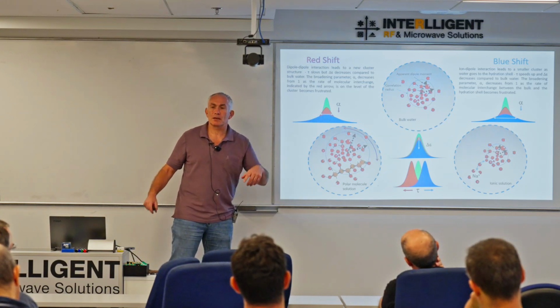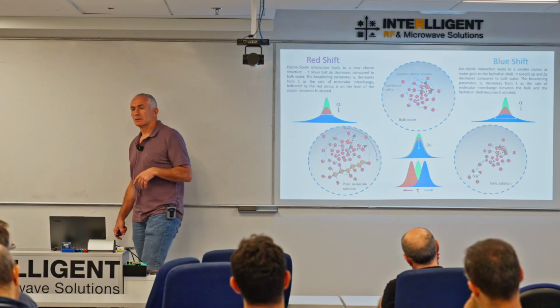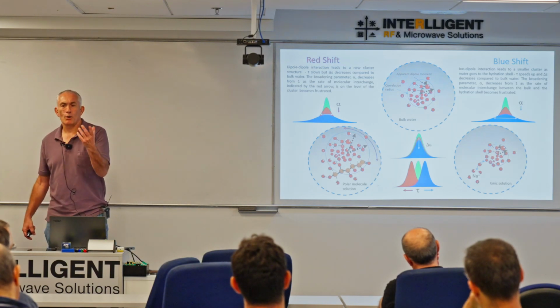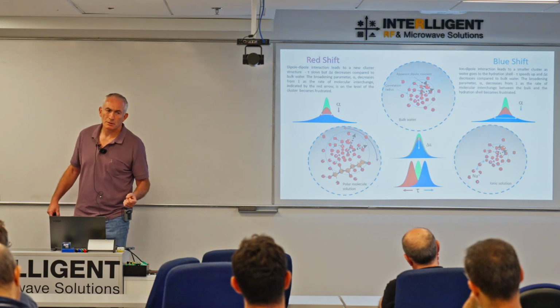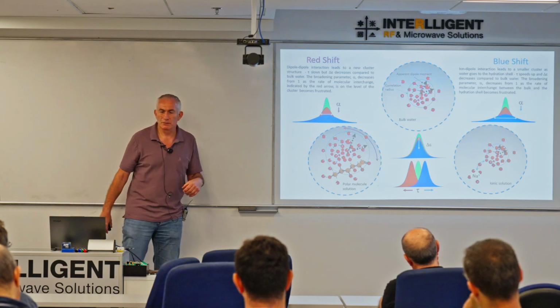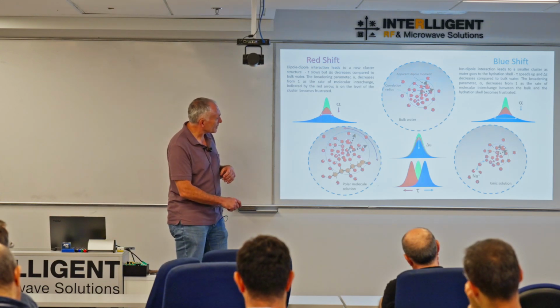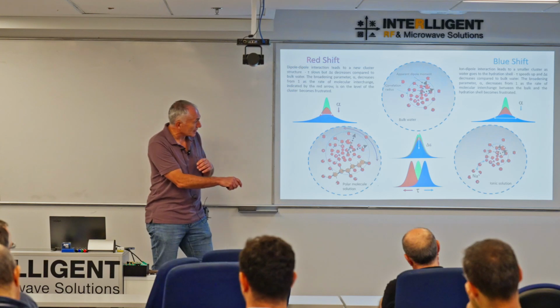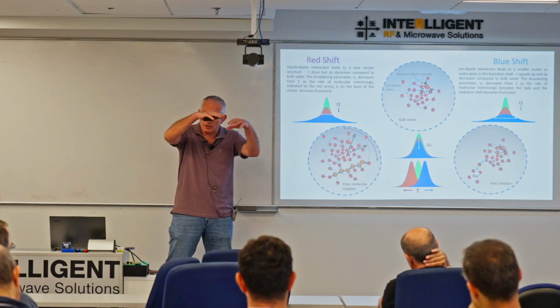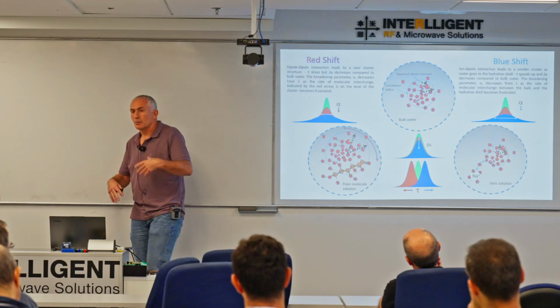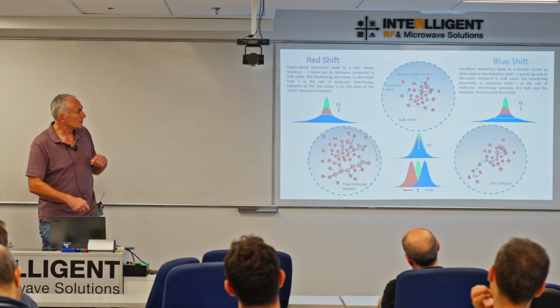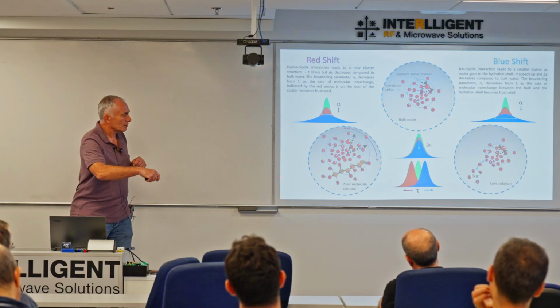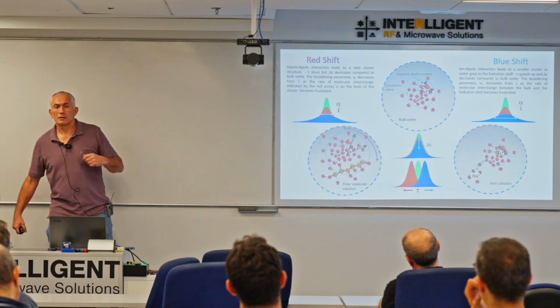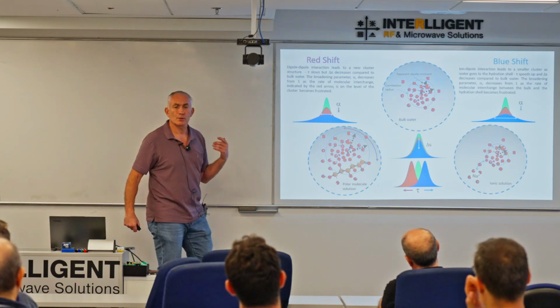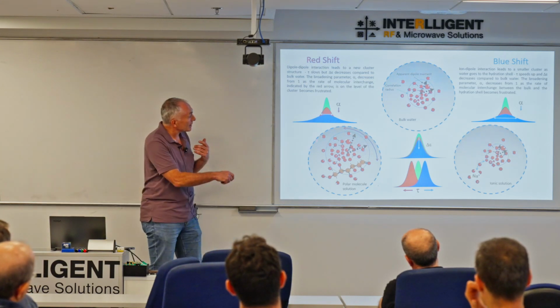But if I put something else inside there, like a dipolar material, like glucose, something which isn't an ion, what I see is something a little bit different. I still see degradation of the dielectric strength. It still goes down. But everything gets slower. The relaxation times shift to slower times, lower frequencies. And once again, I see the broadening.